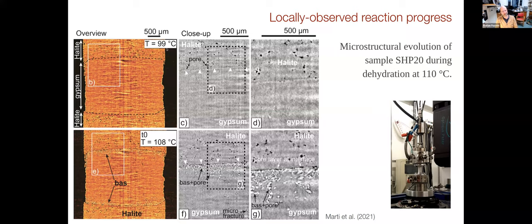The sample is at 99 degrees Celsius here, still during heating. We heat it up to 108, and you zoom in even further here, and you can nicely see this interface. This is half a millimeter. Now, as we reached 108 degrees, and that was only a few minutes later, you can see the reaction is starting to happen here, right? So we expect this gypsum to dehydrate, just as I showed you earlier.